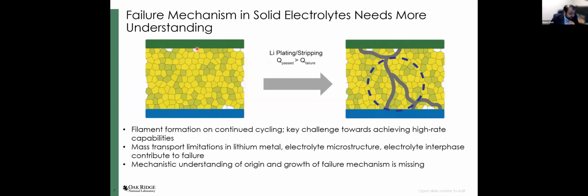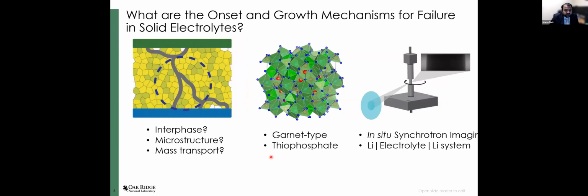If you take a solid electrolyte and couple it with lithium metal anodes, and you cycle it long enough, literature has shown that we form these things called filaments. Essentially, it's lithium metal propagating through the solid electrolyte thickness. And it is not exactly clear why this happens. The mechanistic understanding of why it happens is not clear. And so what I was doing is targeting a couple of very fundamental, promising solid electrolyte alternatives and using in-situ synchrotron techniques to understand whether it is the interface, the microstructure, or the mass transport in the lithium metal anode itself that is causing these failures.